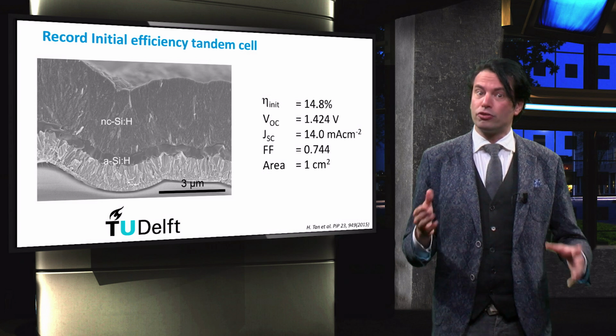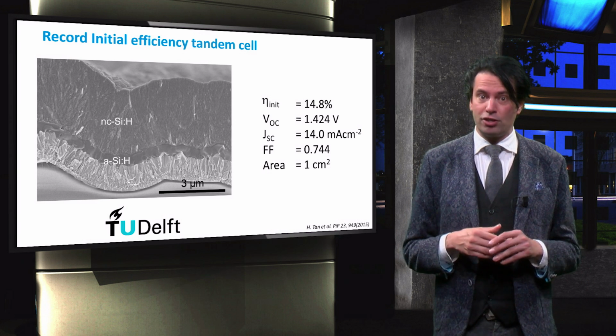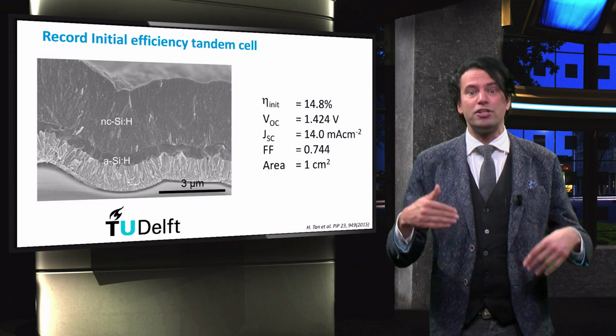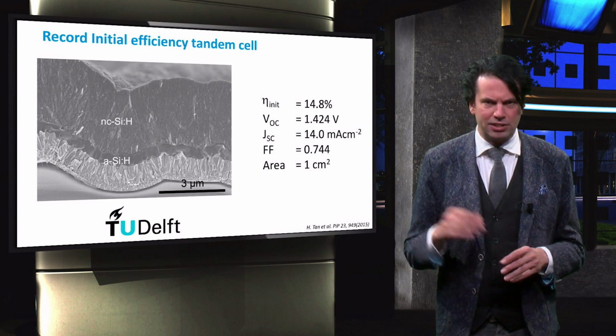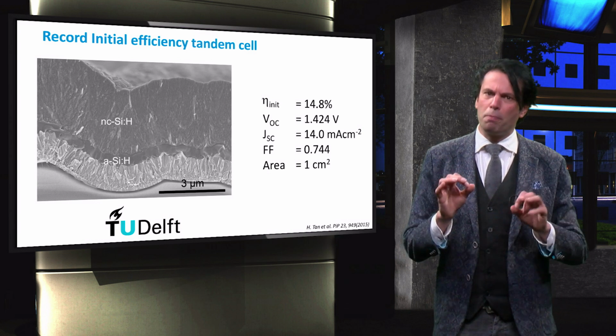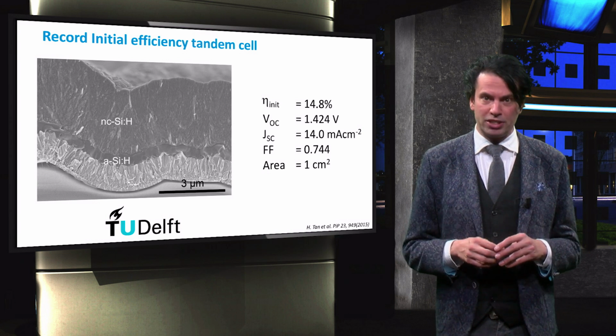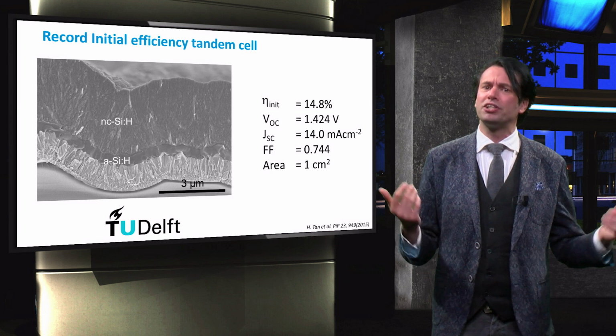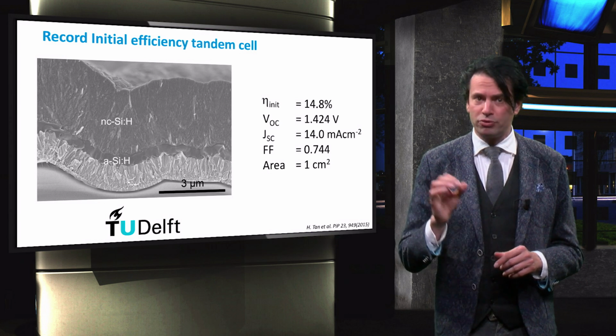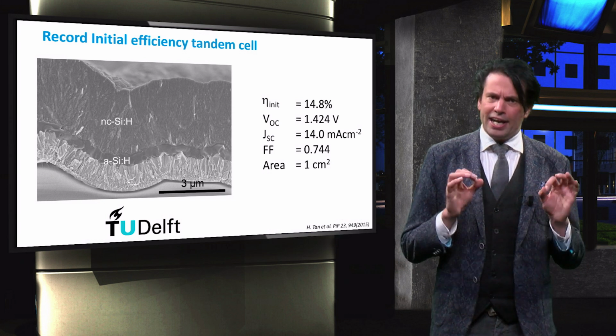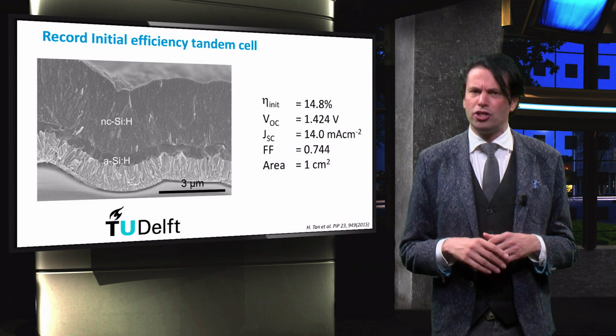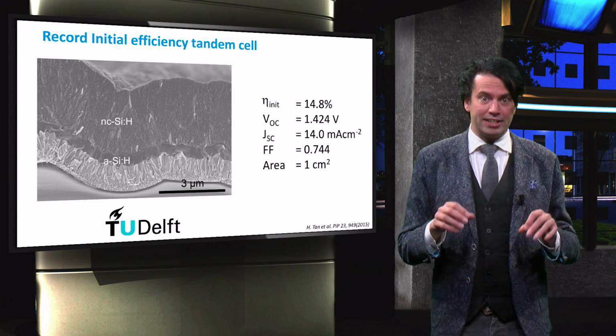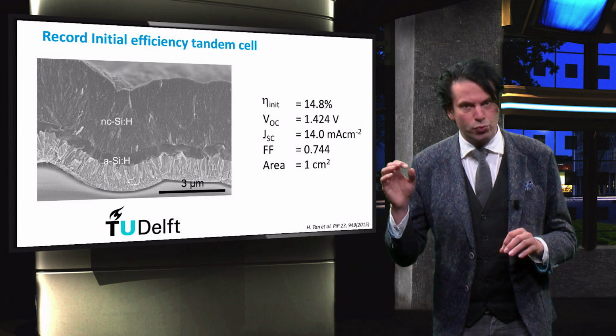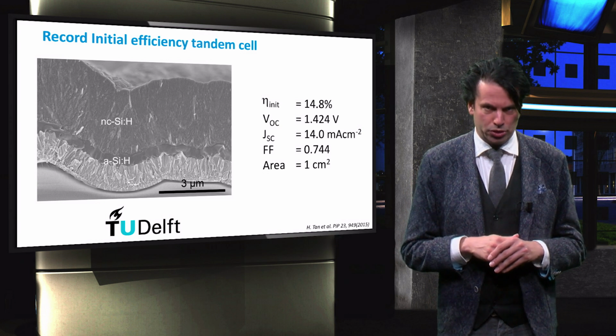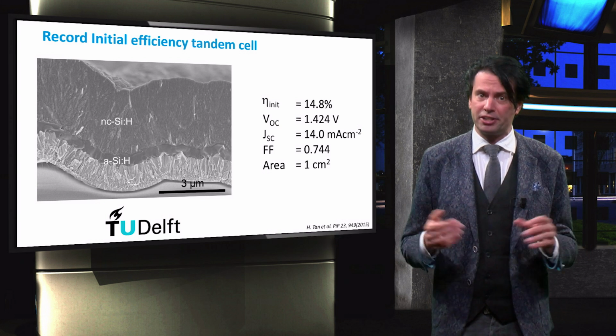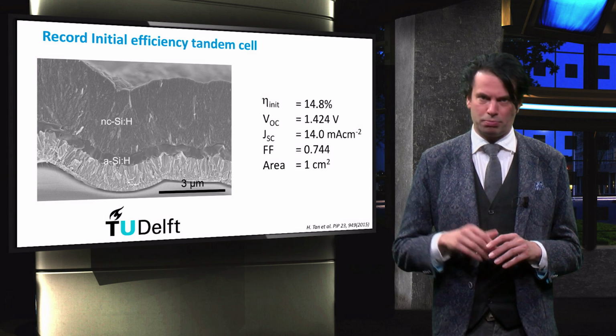Another concept for micromorph tandem cell was discussed in the video lecture on surface roughness. We discussed the integration of modulated surface texturing in the glass substrate, the TCO surface and the amorphous silicon surface as developed at the Delft University of Technology. This approach resulted in a good light management in combination with the growth of high-quality nanocrystalline silicon, without defect-rich filaments. In addition, in the device shown here, a double layer of hydrogenated indium oxide and intrinsic zinc oxide as front window layer has been introduced.